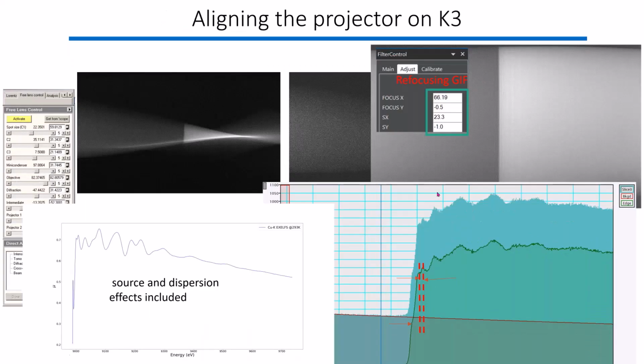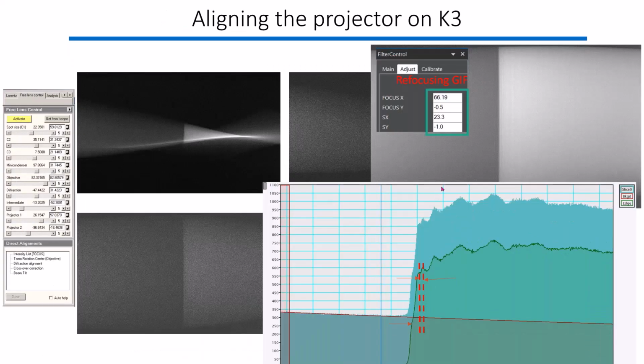So you adjust the crossover using the free lens control, and then correct. Which I don't think has anything to do with the chromatic aberration itself. Of course, between the zero loss and the K edge there will be a difference in focus, but that's a very stable difference. So I'm not concerned about that for the moment.